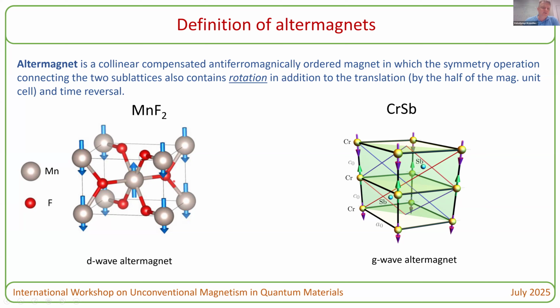Why do these non-magnetic atoms make this material altermagnetic? Because if you think about possible exchange interaction between next nearest neighbors within one of the layers, for example, these two or these two, we see that in the first case, the bond which connects these two next nearest neighbors goes through the non-magnetic atoms, and we can assume some superexchange mediated by these atoms.